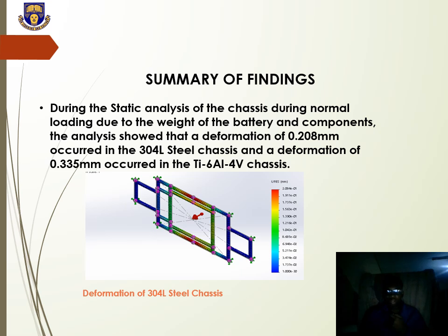Then these are some of the summaries of the findings that were taken from the simulation, static loading and all that. So on the slide we have the deformation of the 304L steel chassis, from the static analysis of the chassis during normal loading due to the weight of the battery and components. So that's simply due to the weight of the battery and components without any passenger on board. We found out that the total deformation on the 304L steel chassis was 0.208 millimeters, and the deformation on the titanium alloy chassis was 0.335 millimeters.